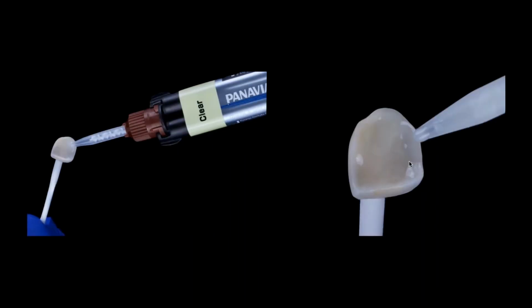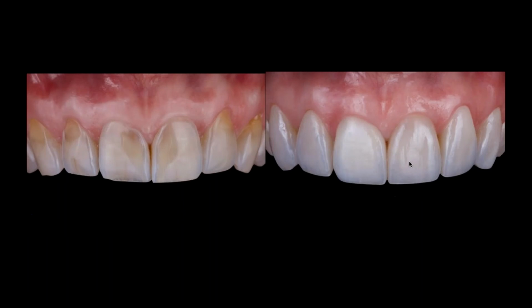tooth surface. So independently of what cement system you use, I like to make sure that I have a clean tip, that the material, the base, and the catalyst is coming even from both segments of the syringe, and that I fully fill the intaglio surface of the restoration. So when I place it, I have that flow of the excess 360 degrees around, so there are no bubbles, and there's a really good sealing of this indirect ceramic restoration.